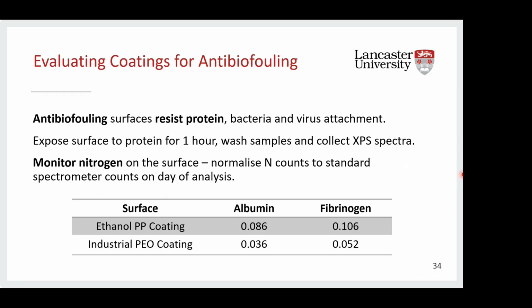In our experiments, we exposed our ethanol plasma polymer coating and the industrial coating to each protein individually for 1 hour. Then we used XPS spectroscopy to monitor the nitrogen content on our surfaces. Prior to our protein tests, our samples don't actually contain any nitrogen. Hence, you can assume that any nitrogen afterwards is relating to that protein adsorbing to the surface, because proteins obviously contain nitrogen in their structure. This table here then displays the nitrogen counts, and these have been normalized to a gold standard within the spectrometer. With XPS, the counts will vary naturally day to day, and we're collecting data over various months that we need to be able to compare.